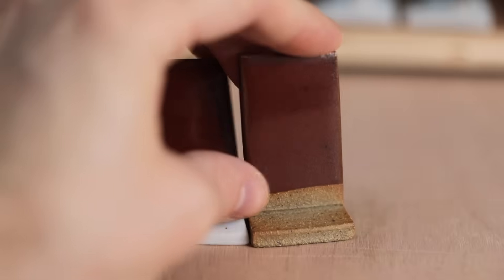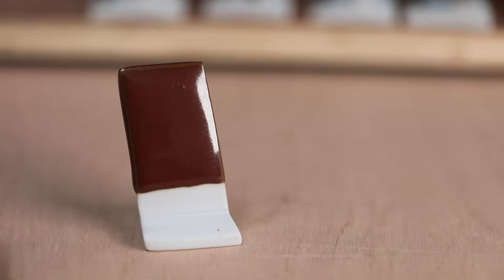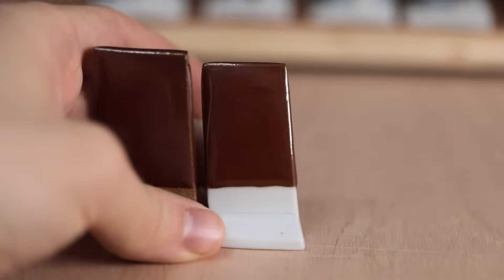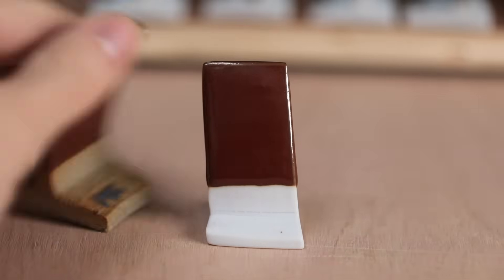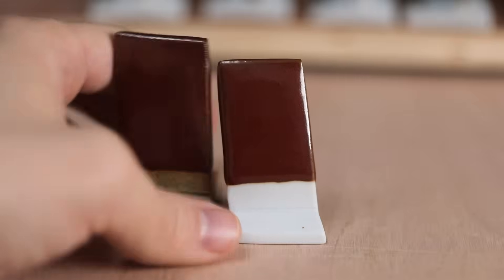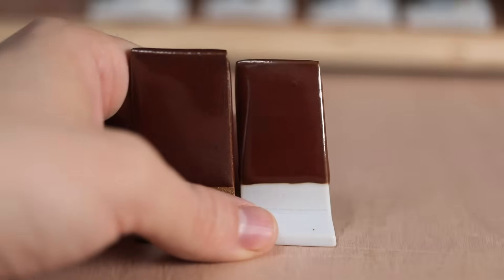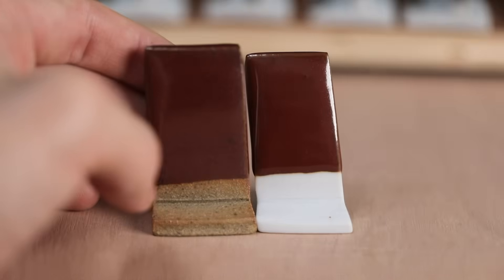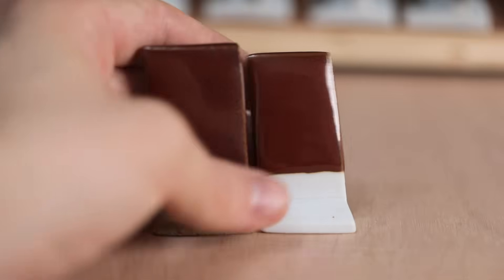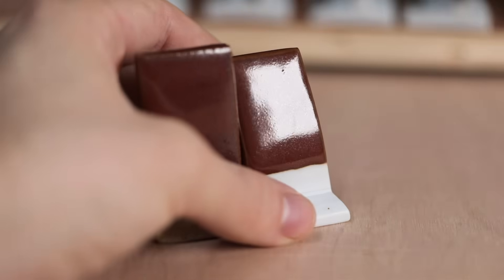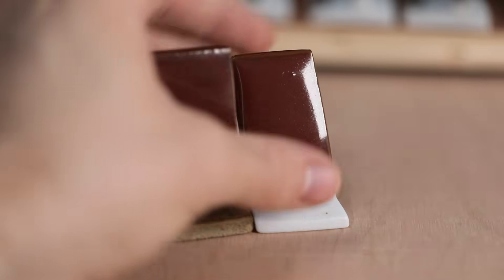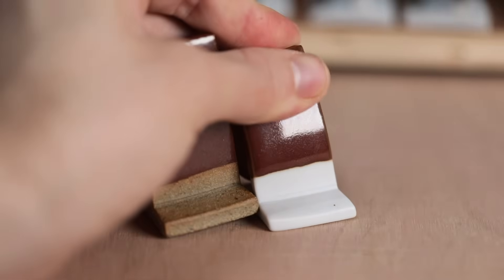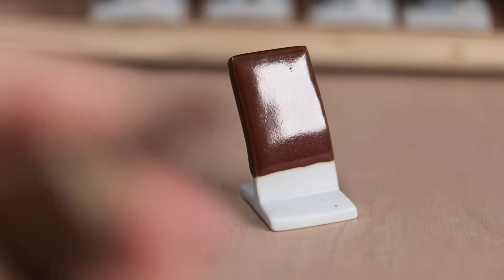The next is a red, which I really didn't expect to like, but I really do, especially on the stoneware, as it isn't quite so vivid, and I can see it matching the white and black quite nicely. The red hue in this instance just comes from about 12% red iron oxide, and this is another glaze that has a wonderful feel, it's so smooth, and the surface again is slightly mottled with other specks of black and grey. It also appears to be a bit more shiny on the porcelain, but it's certainly usable, and that's a factor I wanted with all these new glazes, is that they needed to be usable on both porcelain and stoneware.